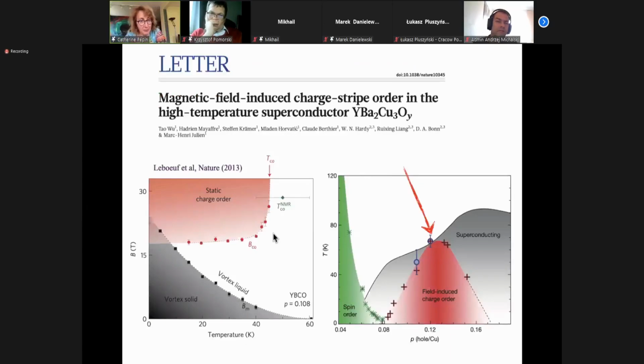Okay, the effect of magnetic field is very unusual in this material. As I said, charge order is stabilized by magnetic field. Here is an ultrasound experiment showing it. You see magnetic field above 17 Tesla. You stabilize 3-dimensional now charge order, uniaxial. And what is very unusual is see this temperature. Is non-existent, so it's flat. So it goes from superconductivity, coexistence, but charge order is going poof like that in one way with no temperature dependence.